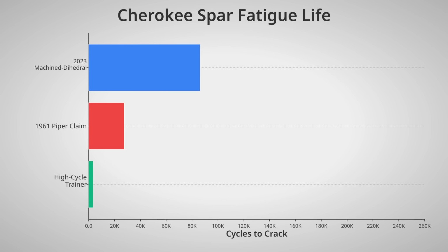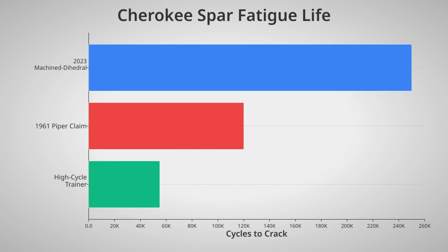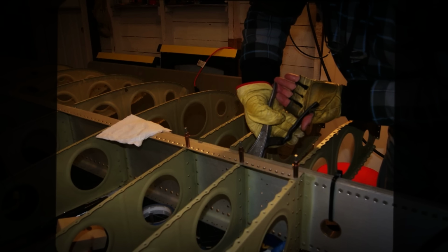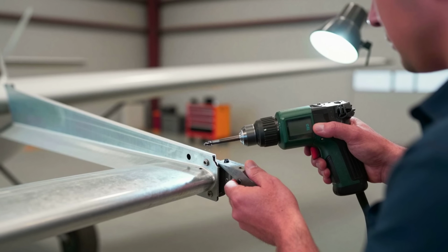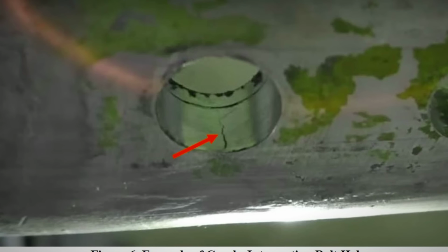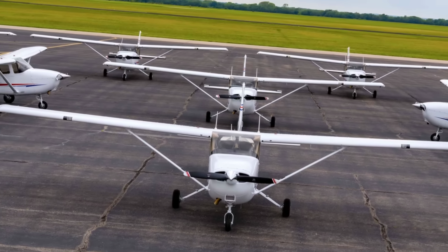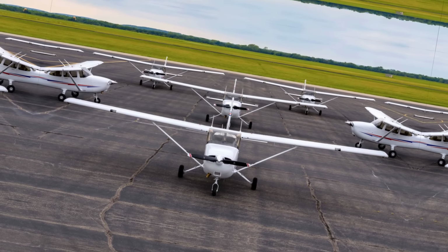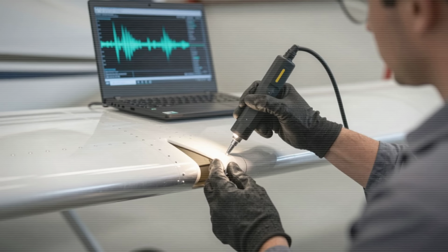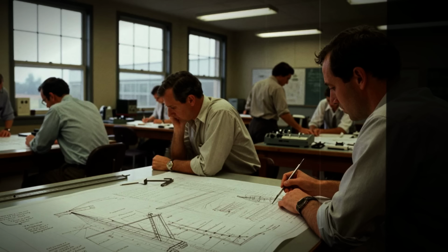Machined dihedral test pieces, introduced decades later, last more than twice as long. The cold bend process, once defended as a cost-saving shortcut, embeds a permanent tensile field at the exact spot where the bolt hole will be drilled. That's the weak link. In service, especially under the high-frequency cycles of training operations, cracks start there and grow unseen.